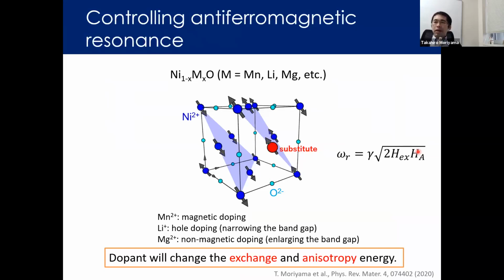Okay. So from here, I would like to show how we can control the antiferromagnetic resonance. Based on the resonance equation, if you want to control the resonant frequency, you need to modify either the exchange field HEX or the anisotropy field HA. The easy way to do that is to dope some cation into nickel oxide to modify the exchange or anisotropy. So in this particular study, we doped manganese, lithium, and magnesium cations into nickel oxide and then see how the resonance is controlled. Here, the manganese doping is considered the magnetic doping. The lithium doping is actually hole doping, which narrows the band gap of the nickel oxide. And the magnesium cation is basically enlarging the band gap of the nickel oxide.